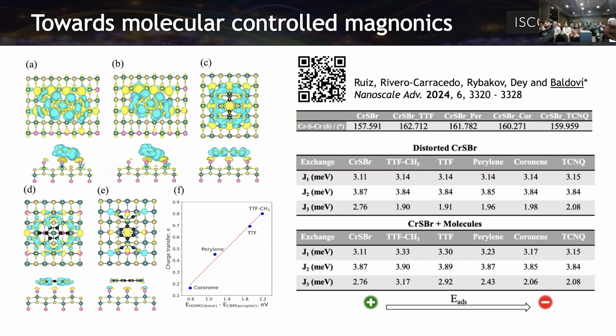So at the end, I will say that they are pretty accurate in terms of prediction, in terms of getting a good estimation of exchange interaction. But of course, they are not perfect because we are relying on several assumptions to make this more efficient, no? Because we start from ab initio, we go with tight binding, and in all these paths, we are making some assumptions that are changing. But I will say that we can go very, very close to the results, like for exchange interaction, for example, that are key for the magnon dispersion.